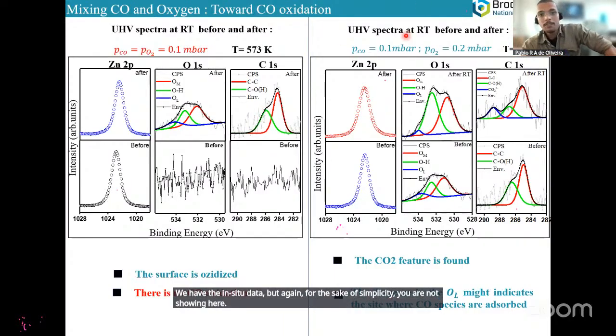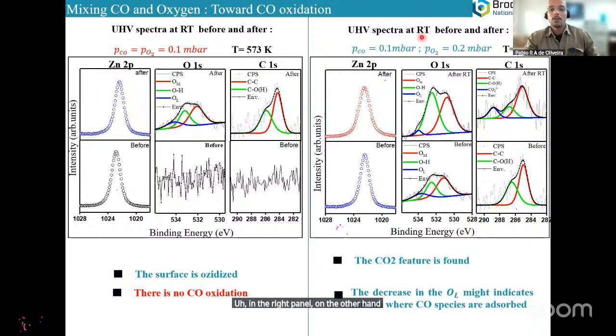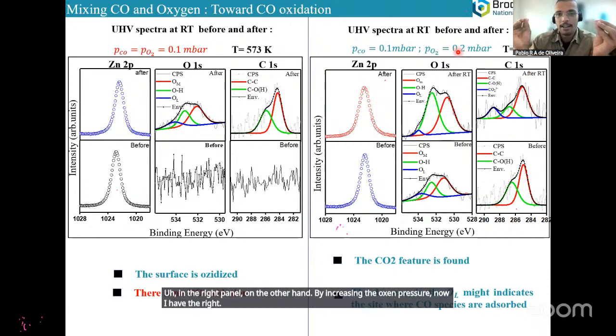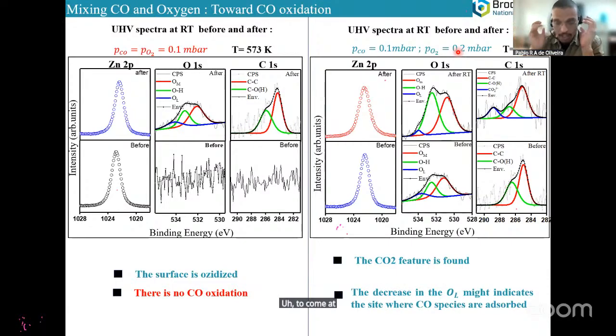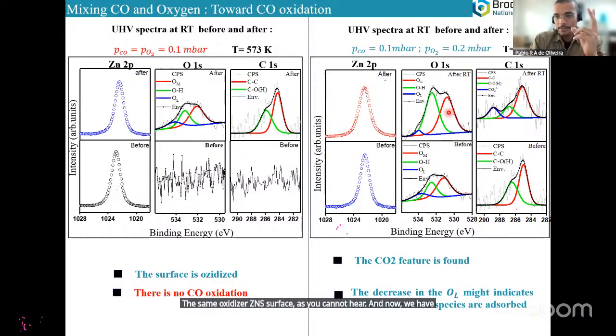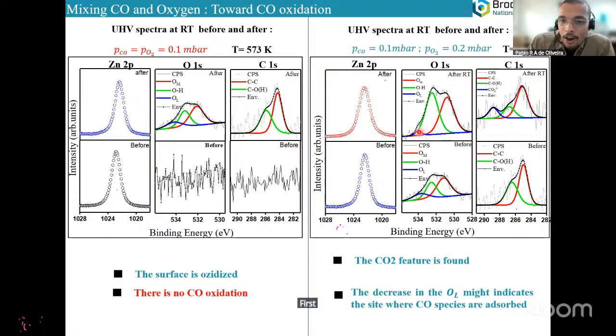And the right panel, on the other hand, by increasing the oxygen pressure, now we have the right stoichiometry to get the CO oxidation. We just use the same oxidized ZnS surface, as you can note here. And now we have two interesting features. First, the oxygen lattice content is decreased. And now you can obtain the CO2 fingerprint. There's a solid peak on the left.